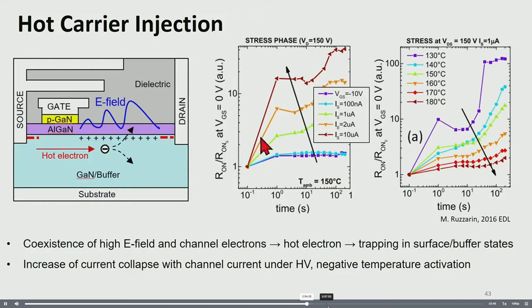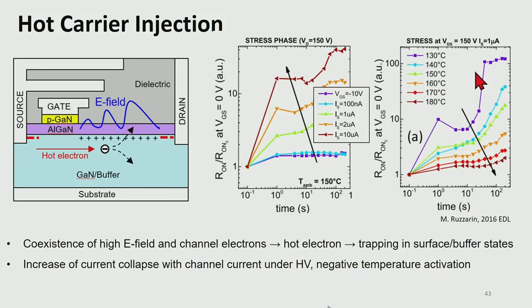If you see this center figure, the RDS,on was monitored as a function of stress time under high voltage semi-on state stress. With increasing the channel current from 100 nanoamps to 10 microamps, the RDS,on degradation is accelerated, because higher channel current means a higher number of channel hot electrons. And this hot electron effect has a negative temperature activation, because the increase in lattice scattering at high temperature can suppress the hot electron generation. So if the dominant electron trapping mechanism is hot carrier injection, the dynamic RDS,on performance can actually be improved at higher temperature, as you can see in this figure.